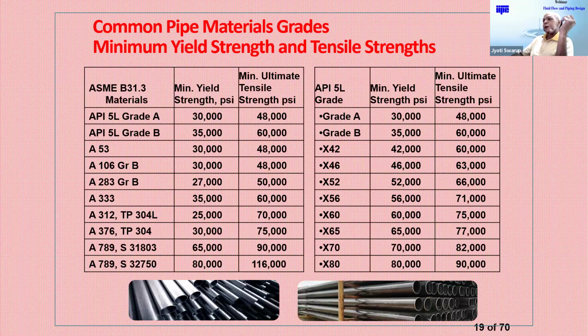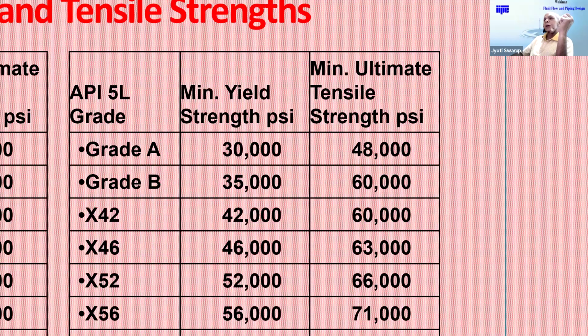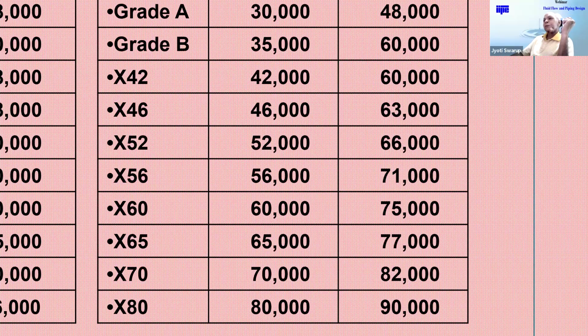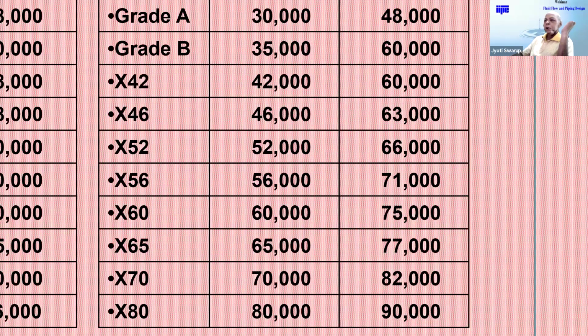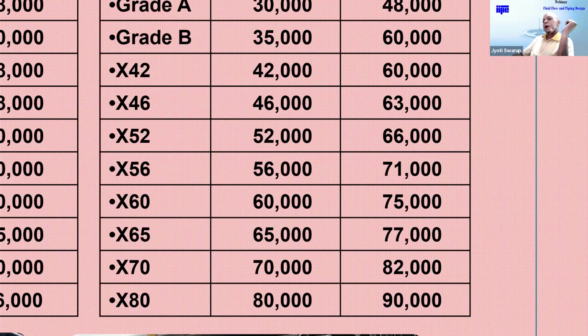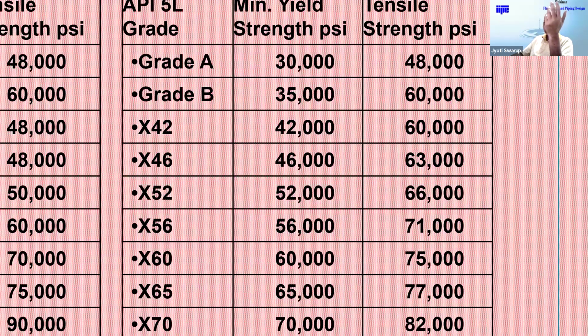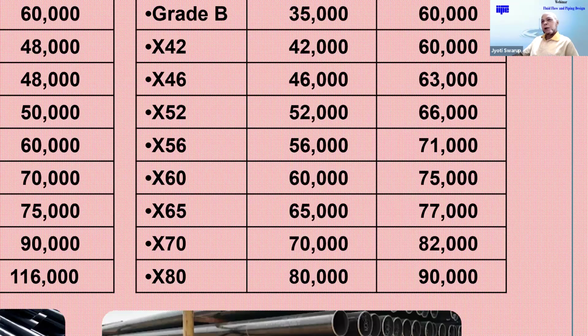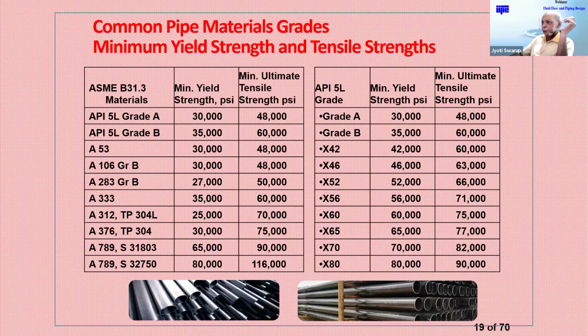The other code that we mentioned was API 5L, which gives the thicknesses, and it does not give the strength directly. It says X42 grade means 42,000 is the yield strength of the material. So we have X80 grade, which has a yield strength of 80,000 psi. These are all carbon steel pipes, not stainless steel. For pipelines or critical applications, we use API grade 60 or grade 65 instead of a piping grade like API 5L grade B or A106. So for pipelines we always use API 5L pipes, while for piping we use ASME A106 or whatever pipe grade that we have. Pipelines can be high strength material ordered to the spec of the client, and of course ordered in bulk sizes. This actual grade may not be available in the market.